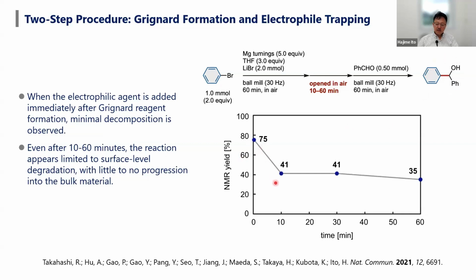Surprisingly, after 10 minutes of opening, this Grignard reagent was still alive. Of course, the product yield decreased, but 40% of product could still be observed. This means that during this opening time, the surface of this peanut-butter-like reagent can decompose, but the inside is not very unstable.